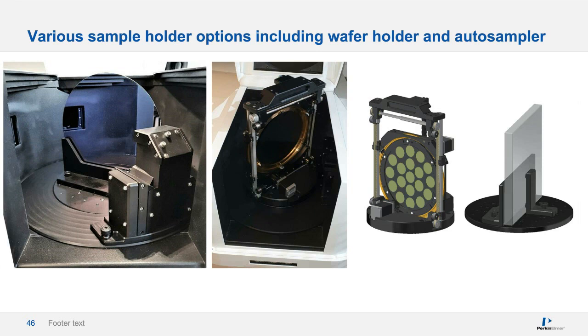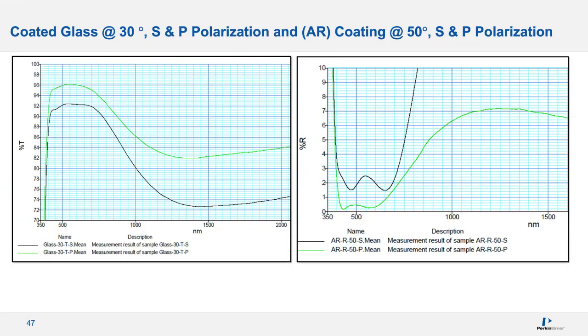And now for some TAMS data. In this case, coated glass was measured in both transmission and reflectance mode at 30 degrees and 50 degrees, respectively. As expected, the AR coating shows low reflectance at about 400 nanometers. However, this depends upon which polarization state was used for the measurement.